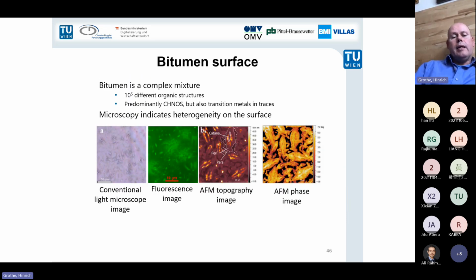And we were applying atomic force microscopy in different modes, which is seen here on the right-hand side, and we were combining that with information from fluorescence microscopy. We already know that our system shows a fluorescence signal. We already know that the aromats are responsible for the fluorescence, and it's particularly the resins and the small aromats, which show a very strong fluorescence signal. And here we can really recognize that these materials obviously are clustering inside these morphologies, which we have already observed with the AFM.